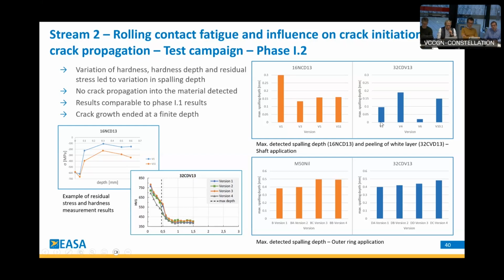Now the question is, based on the statistics, if this will remain if we test 10, 15 or 20. There is a small result noticed, but I have to say it could also be that for the three tests, maybe it is only one result. But there is a difference to the outer ring application. The observed influence is not that drastic as for the shaft, for example. And you see on the right side bottom, you see it for the outer ring application. It's always plus minus 0.4, for example, here. So the spalling depth on this is more or less comparable and the same.